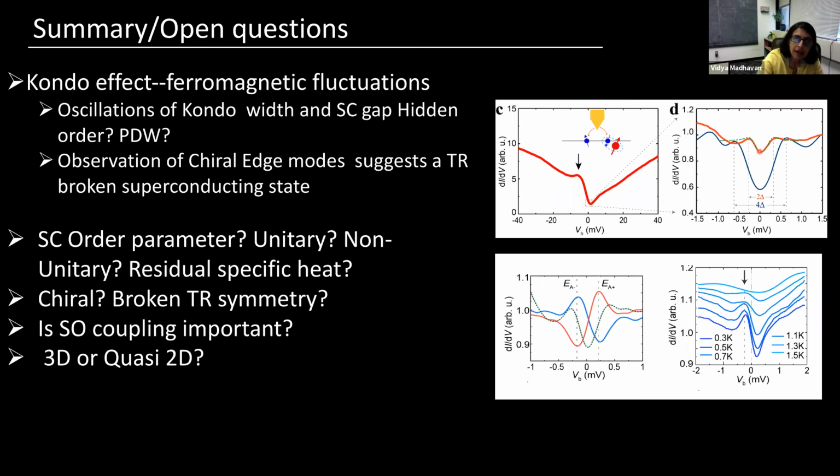One possibility is that this gap is shallow because the gap is filled with surface states that you would expect for a chiral superconductor. The problem is usually when you see vortices with STM, your signal to noise comes from the contrast between some kind of vortex bound state and the rest of the superconductor. Because of the presence of these surface states, it's very hard to see the vortices in the system. I personally think we should cool down to even lower temperatures and turn on the field again and check. We don't have that capability. Maybe someone else can do it. Thank you.